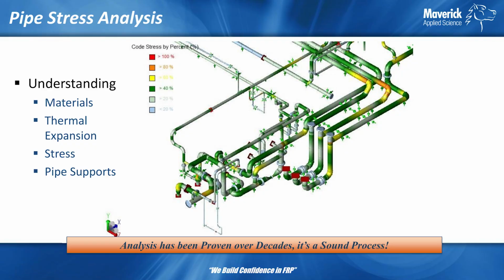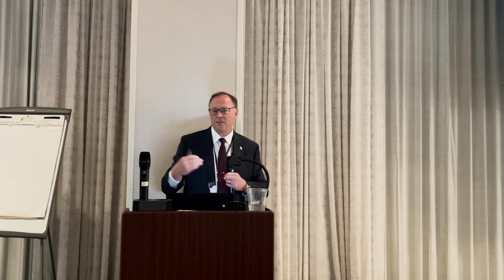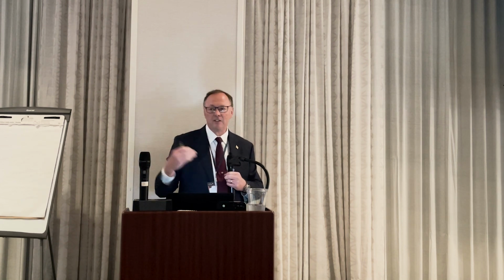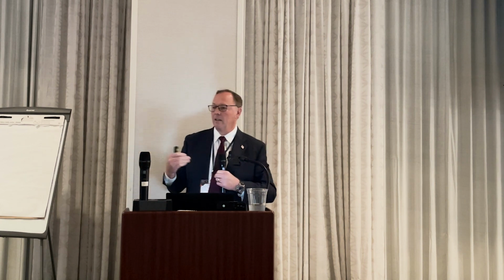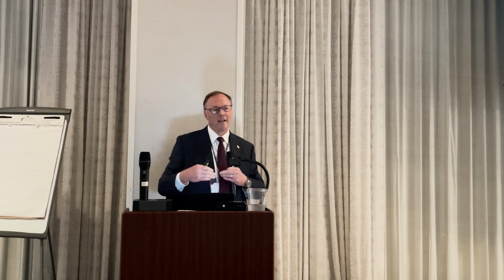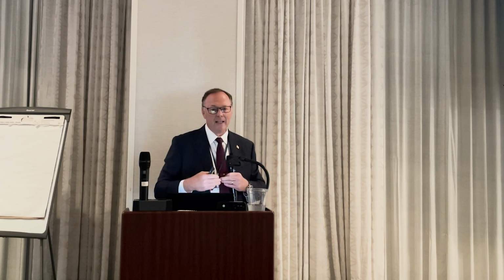Pretty much, I would say that if you're in chemical processing, so like a non-wastewater application, almost every system needs to have pipe stress analysis, because we're usually running something like a 50 to 110 psi, 150 psi system, and temperatures are going to range from 150 to 200 degrees Fahrenheit. In chlor-alkali, a lot tends to run between 180 and 200. These systems need to be analyzed formally because they're expanding and contracting.